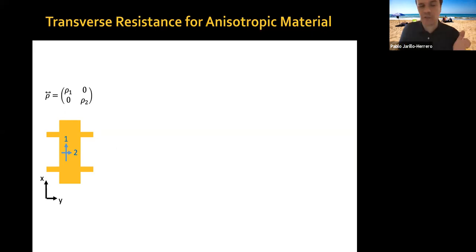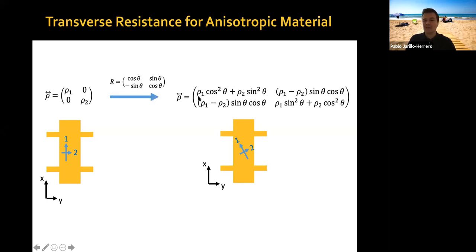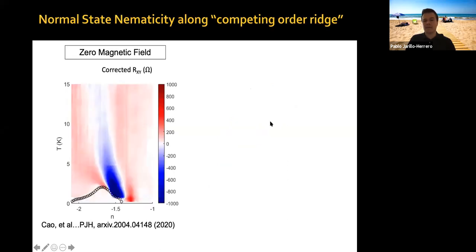And of course, if the material is isotropic, you measure zero Rxy resistance no matter what. However, if your anisotropy axes are rotated with respect to your device axes, then you have to do a transformation of your resistivity tensor. And you can pick up a finite rho xy, a finite transverse component, even at zero field, as long as you have a resistance anisotropy, rho one minus rho two is different from zero, and you are not at a zero or 90 degree angle. So this is something that indeed happens in our devices.